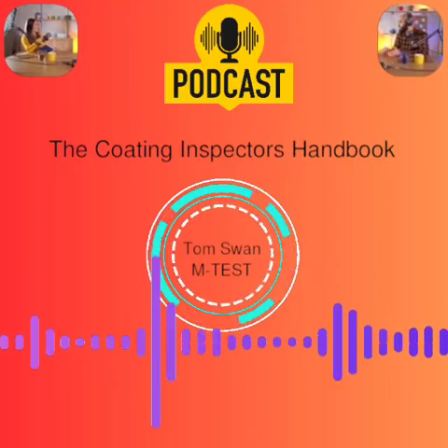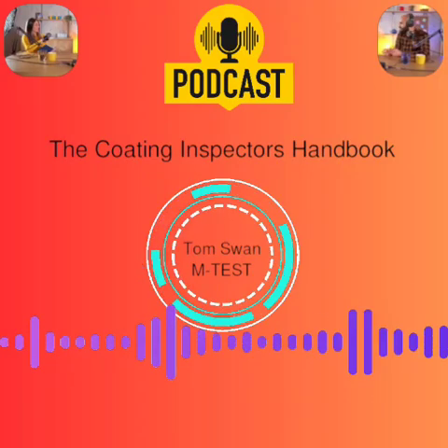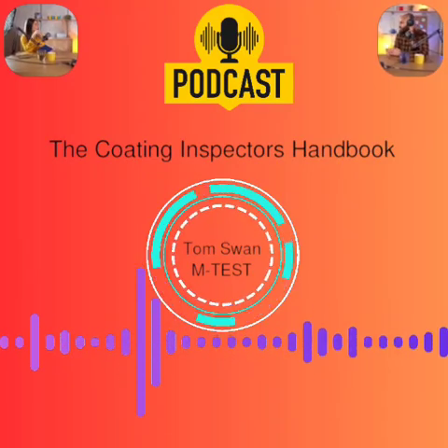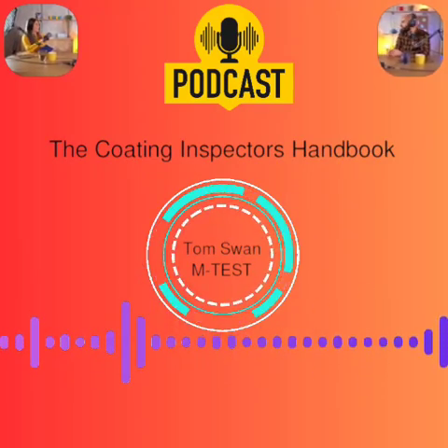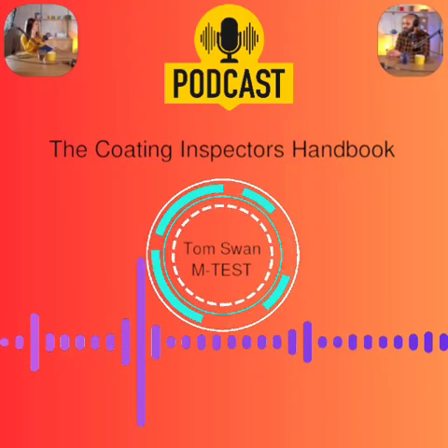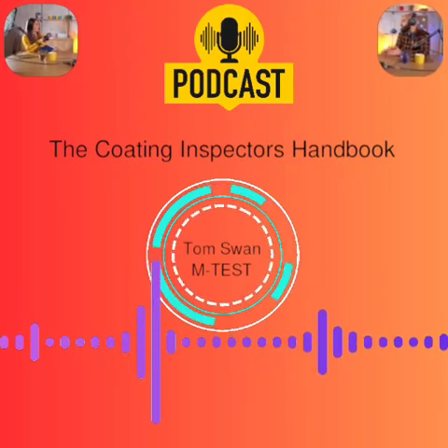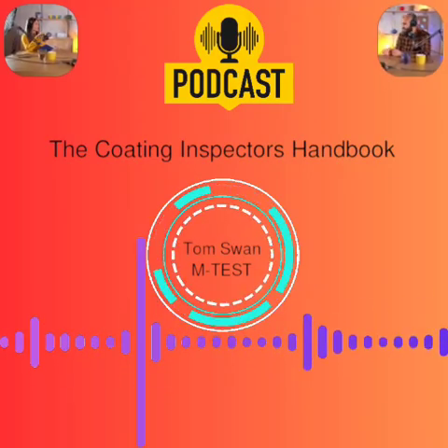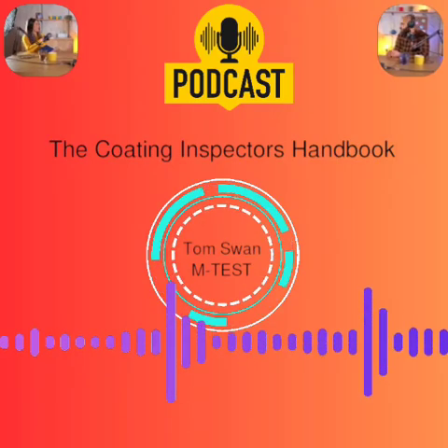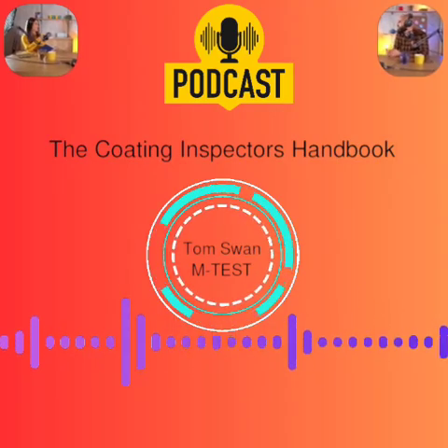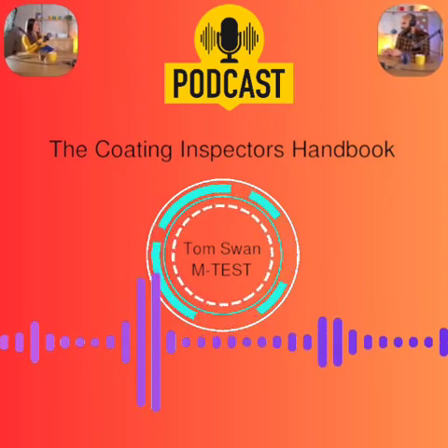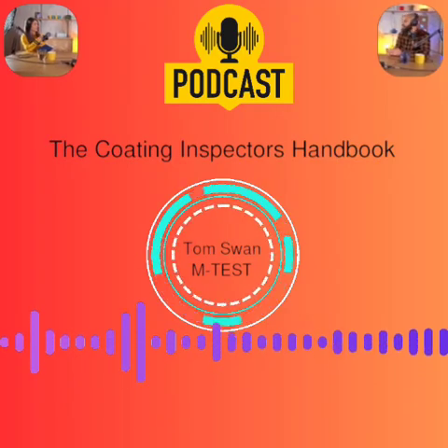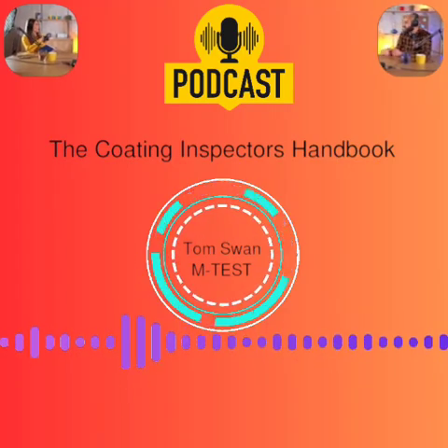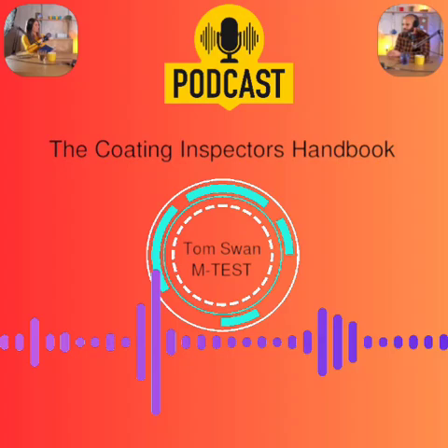Which tester do you use, low voltage or high voltage? General rule: a low voltage sponge tester for coatings up to about 20 mils on metal. A high voltage spark tester for coatings over 20 mils on metal and for testing on concrete. How do you set the voltage for high voltage if the spec doesn't say? Check the PDS first. If nothing, the rule of thumb is 100 volts per mil of DFT. Or use NACE formulas: V = 525 times the square root of mils up to 30 mils, V = 1250 times the square root of mils above 30 mils.